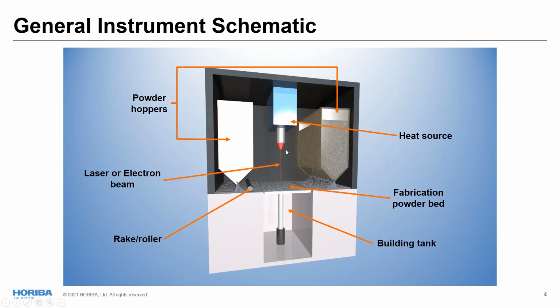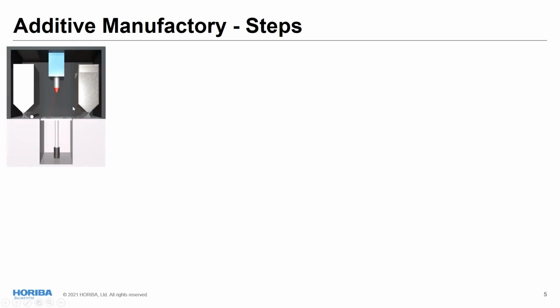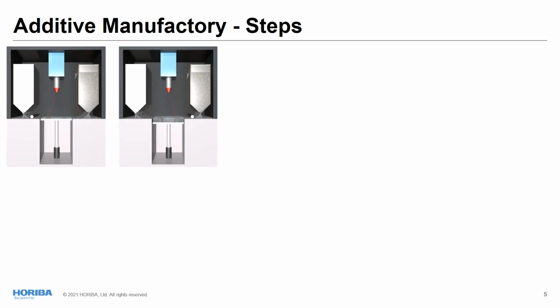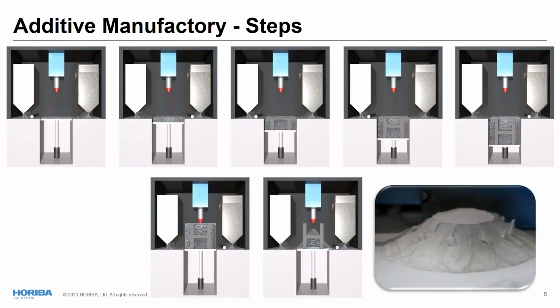Or if it is electron beam, you're going to have vacuum in this chamber. And you have the powder hoppers where you have your metal powders that will be delivered, and a rake that spreads this powder and makes a bed, what we call the fabrication powder bed. Your heating source will sinterize the particles, which is actually printing a layer. The way the process happens is, you have the first layer deposited, and then your laser goes through and sinterizes the powder where it should be and prints the first layer. Then the stage moves a little bit down, and you have the sinterization of the second layer, and so on.